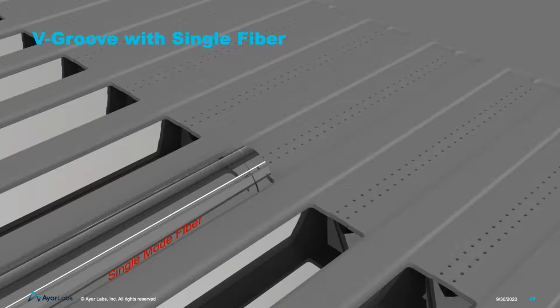Speaking of physical integrity, note that the fiber will be epoxied into the Vgroove. Therefore, the adhesion between the optical fiber, Vgroove, and the epoxy itself is very important. As the wafer is processed through the die prep and flip chip steps, it is important to keep the Vgroove region clean. For example, the region, including the spot size converter, needs to either remain clean or to be cleaned after dicing. Additionally, if flux is used during the flip chip process, the flux should not contaminate the optical facet. Finally, it is important to avoid filling this region during the capillary underfill process. This includes either epoxy bleed out or outgassing of the epoxy.